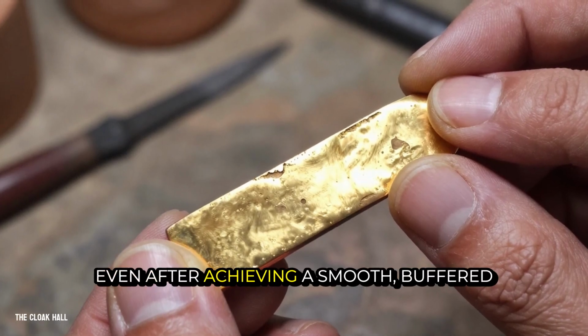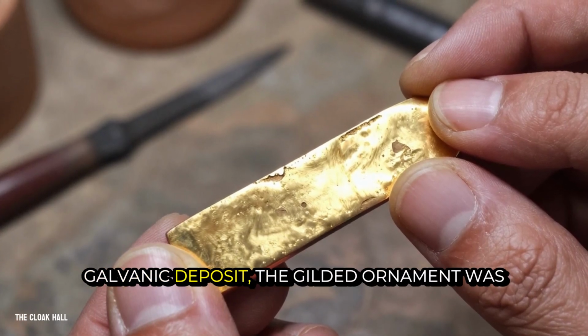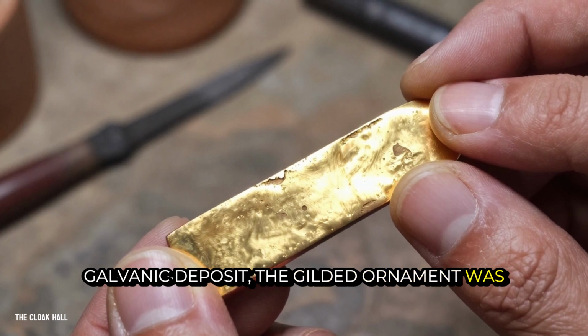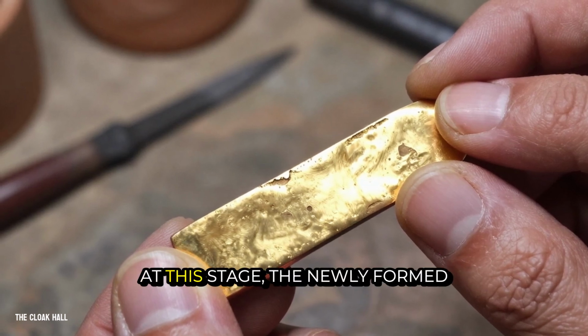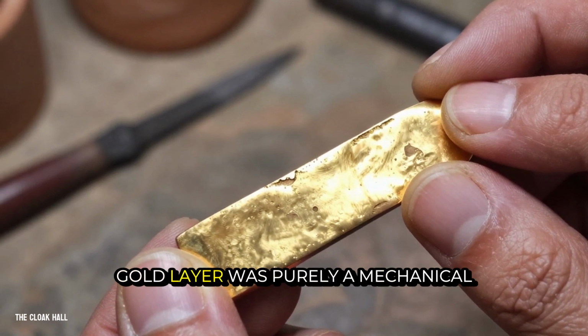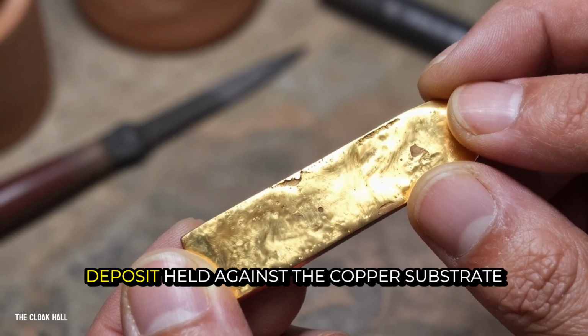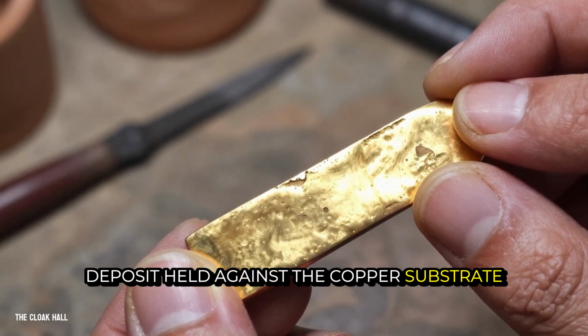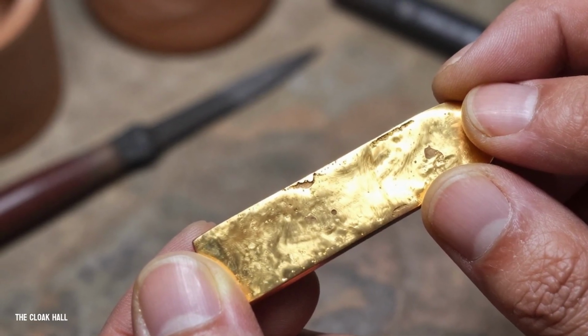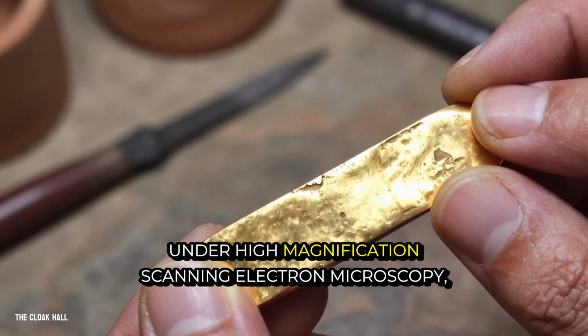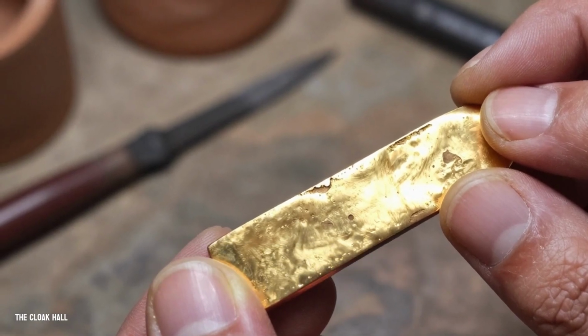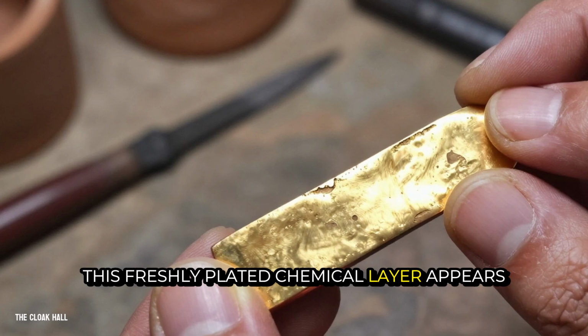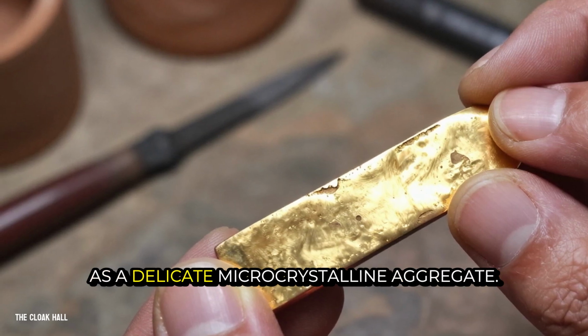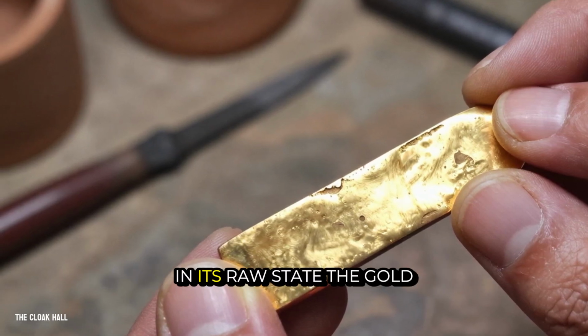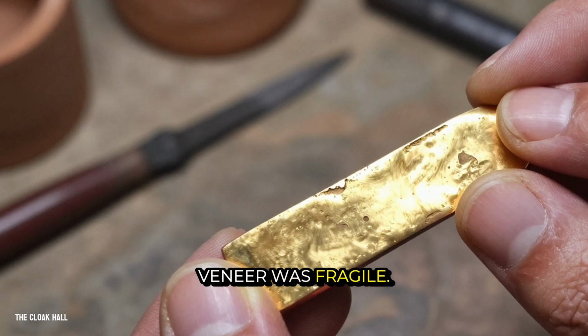Even after achieving a smooth, buffered galvanic deposit, the gilded ornament was not yet finished. At this stage, the newly formed gold layer was purely a mechanical deposit held against the copper substrate by weak surface adhesion. Under high magnification scanning electron microscopy, this freshly plated chemical layer appears as a delicate microcrystalline aggregate. In its raw state, the gold veneer was fragile.